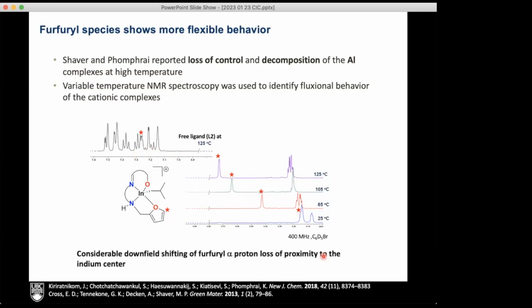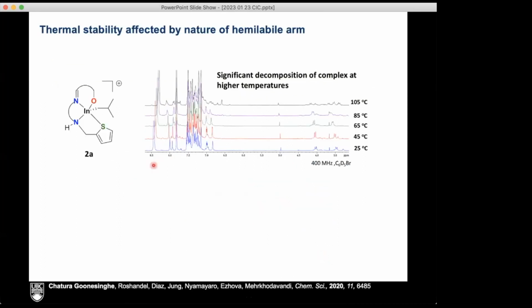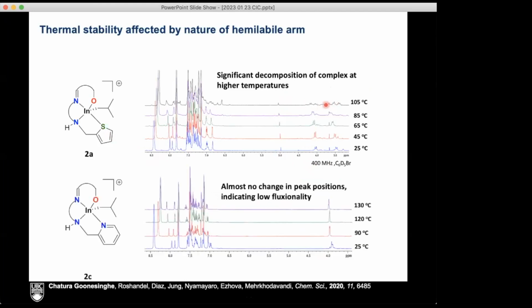In contrast, for the sulfur donor, this was irreversible. So we saw decomposition when we went up to 105. You can clearly see decomposition in the system. And in the case of the pyridyl, we very much didn't see any kind of change. So this was very much a rock in our case.